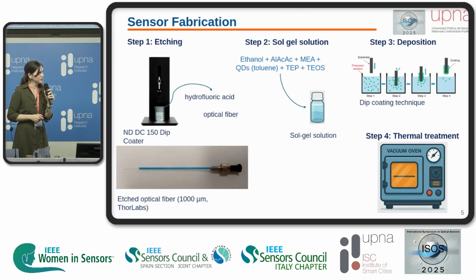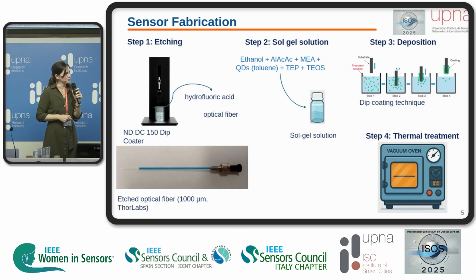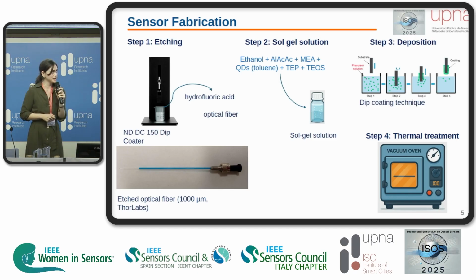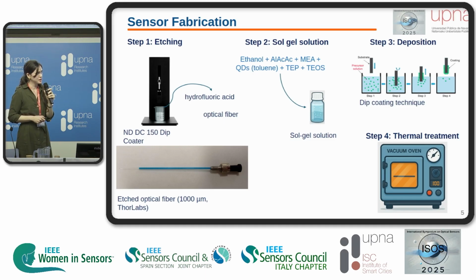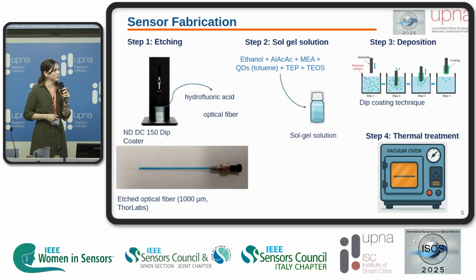Step 2 is preparing the sol-gel solution. The sol-gel is a good host for the material because it avoids its degradation and stabilizes the film. Step 3 is the deposition of this sol-gel solution by dip coating technique, varying the number of layers between 10 and 20 dips in this case.